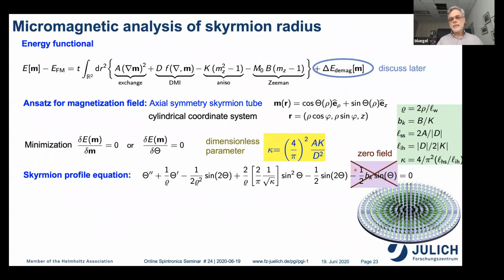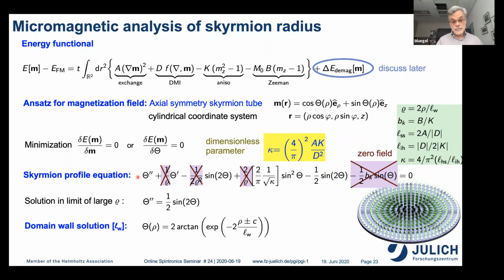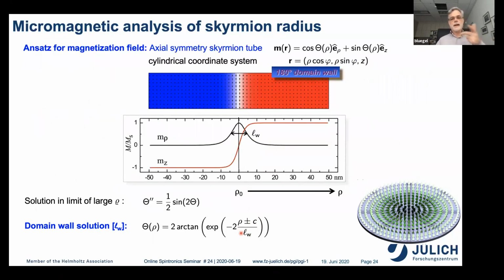I mentioned to you this equation here, okay, you cannot see very much of this equation. But if you look at the limit of large radii, then you can cancel out a few terms. And then this equation reduces to an equation you might have seen before. This is exactly the domain wall equation. And therefore, in a certain regime, the domain wall solution is a very good ansatz for the Skyrmion. And you have maybe a few parameters to optimize the domain wall profile, which is maybe this integration condition C or the domain wall width W. And we are familiar with this domain wall solution.